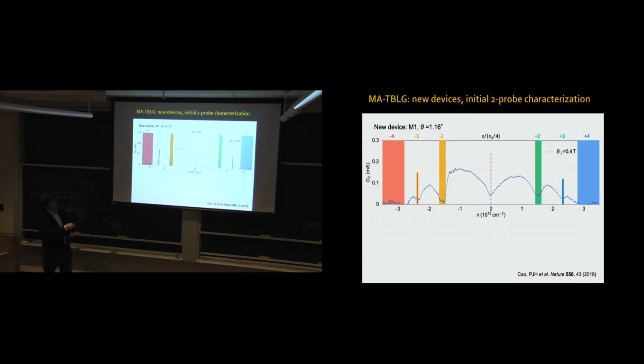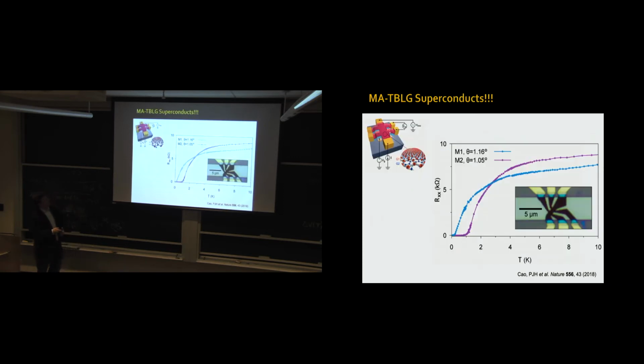We also have stuff at 3 and -3. There's a lot of extra things which I'm not telling you about that also happen in this system when you have other integer fillings of your superlattice. This is in the presence of a small perpendicular magnetic field. If I now remove the magnetic field, not much happens around the correlated electrons, but a lot happens around the correlated holes. So now we switch to our four-terminal geometry measurement, and what happens is the magic-angle twisted bilayer graphene superconducts. These are data from two devices, 1.16 and 1.05 degrees.